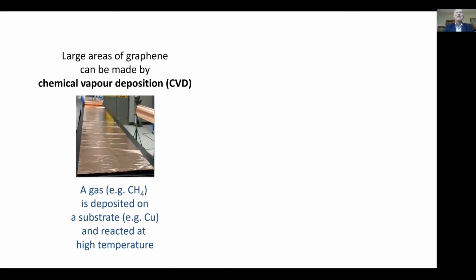One way is something called chemical vapor deposition, where you take a gas, usually methane, a carbon source, and it's deposited on a substrate which helps the reaction, often copper, and it's reacted at high temperature. And if you get it right, you can get a very thin, single atom thick layer of carbon, which, if you're clever, you can then transfer from the substrate onto something else where you want to use it.